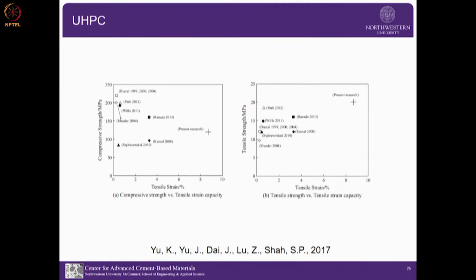Here I have shown the UHPC compressive strength versus tensile strain, because we want high compressive strength and we want high ductility. In the work we did, we were not able to obtain 150, but it's more like 120 megapascal, with considerably higher strain. And if you look at the same results, tensile strength versus tensile strain in tension, this is considerably higher compared to what has been done.